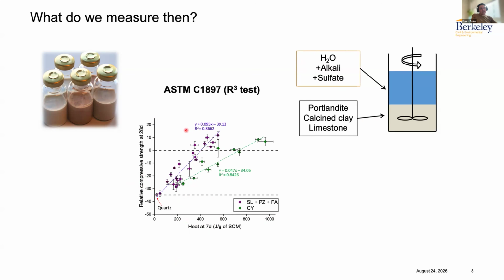And what we have seen, why we like this method, is that there is a pretty strong correlation between the heat evolved during the R3 test or the ASTM C1897 test and the compressive strength that we can measure in a mortar, at least better than what we observe with other competing tests like strength activity index or calcium hydroxide consumption.